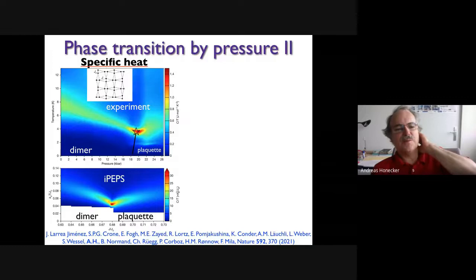And by other methods, you can actually trace that to a first order transition between the dimer singlet and the plaquette state at 0 temperature. So that red spot here is connected by a line of first order transitions to the 0 temperature phases. Well, now that we have developed the methods, we can do the computation as a function of exchange ratio here of the specific heat.